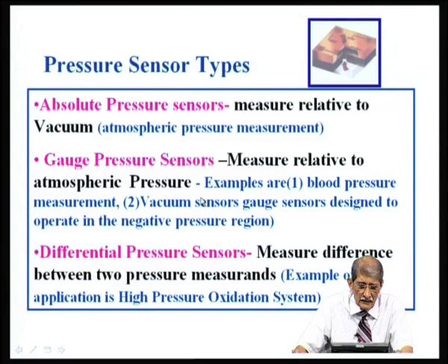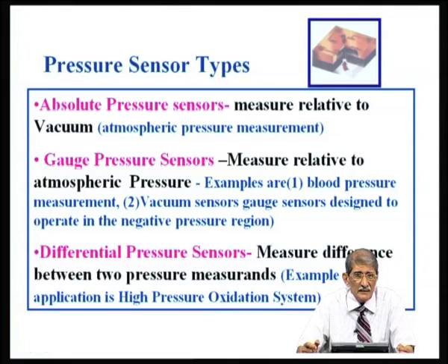Then you have differential pressure sensors, which actually measure the pressure on top and bottom, on both sides of the membrane. These are used when you want to monitor the pressure from both sides and you want to keep a pressure constant across a membrane, and if you want to vary the two pressures: inside pressure 1 bar, outside pressure 1.5 bar, and then inside pressure becomes 1.5 bar, outside pressure you also increase by 0.5 bar. So, the difference is maintained at 0.5, that is the differential pressure.